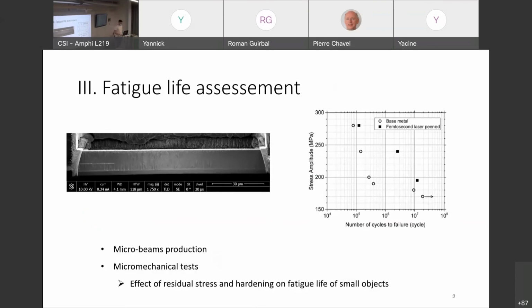And the last part of this work will be to validate this method by assessing the fatigue life of the material. To do so, we will produce some microbeams on which we'll do a micromechanical test by putting a down force on those microbeams, and then measure the number of cycles to failure. And we hope through this validation to know exactly which is the effect of the residual stress on the hardening and on the fatigue life of small objects.